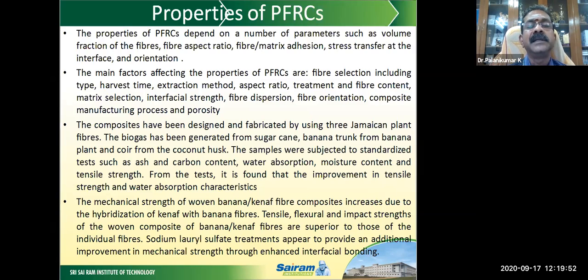The bagasse has been generated from sugarcane, the banana trunk from the banana plant, and the coir from the coconut husk. The samples were subjected to standardized tests such as ash and carbon content, water absorption, moisture content, and tensile strength. From the tests, it is found that there is an improvement in tensile strength and water absorption characteristics.